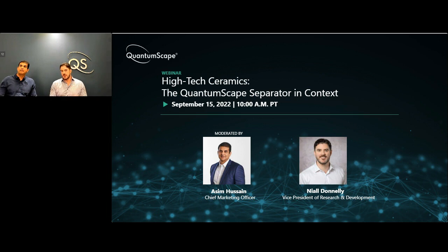Well, it's a great question because it's something that often goes missing in discussions about lithium metal batteries. In many cases, when you assemble a lithium metal battery, you might actually include foil or some lithium metal in the initial assembly. And this gives you a reservoir of lithium that you can continue to use throughout the cycle life of the cell. But in the QuantumScape separator, we actually start off with zero lithium metal at all in the cell. All the lithium exists in that cathode reservoir. And what happens on the first charge of a QuantumScape battery is that the lithium leaves the cathode material, it moves through our separator, and it nucleates on the current collector in contact with our solid-state separator, and it forms a thin layer of lithium metal itself, and then that continues to grow with further charging.